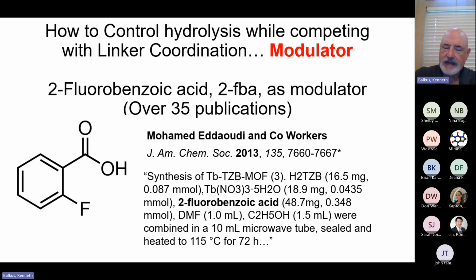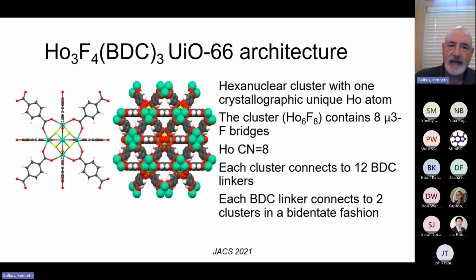Now, a modulator is an additive that you incorporate into the synthesis that would weakly bind to your metal and then allow the cluster to form. It would control basically the crystallization. The molecule that was most frequently used, and first reported by Eddaoudi and coworkers, was 2-fluorobenzoic acid. So he added some 2-fluorobenzoic acid to the syntheses that had been consistently making these dimeric structures, and the first synthesis made this beautiful structure, isostructural with UiO-66.